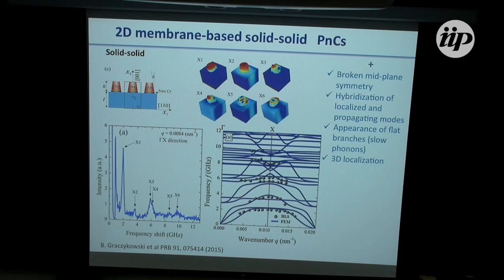there is hybridization and localized modes. There are propagating modes. There are a series of flat branches, phononic branches, which basically says very slow phonons. And there is indication of three-dimensional localization, because, for example, here in this lower mode, the X1 and the X2, the amplitudes are largest inside the pillars, inside the resonators. Right? So this is the macro picture compared to the resonators that you were talking about on the surface resonances. In your case, 1 or 2 nanometers. In our case, 100 nanometers. These are 60 nanometers or so tall.